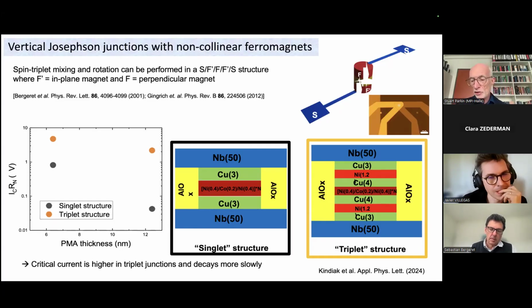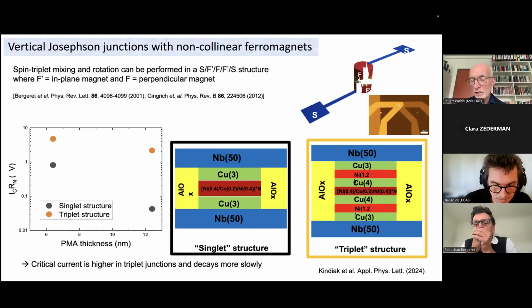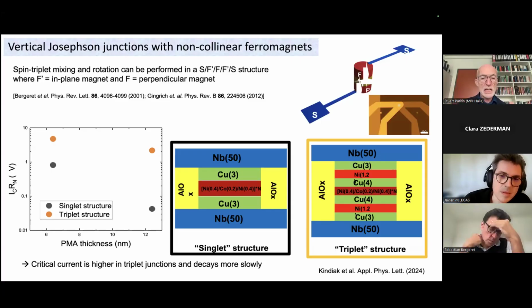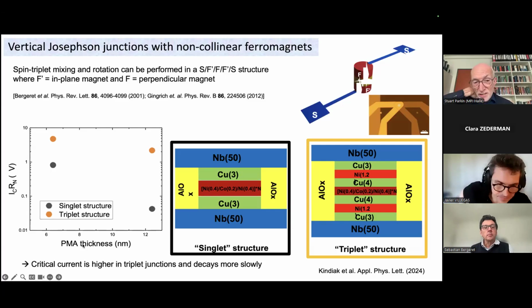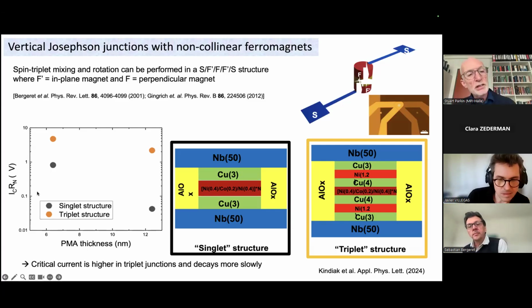So we're going to call this the triplet structure, because now, following Sebastian's prediction in 2001, we can create a triplet supercurrent that will survive over long distances, even though we've got more magnetic material on the right-hand side than in the middle. On the left-hand side, you can see the orange dots correspond to the critical currents for this triplet structure. For the same thickness of the cobalt-nickel-cobalt multilayer, the PMA thickness, the critical current density is increased almost by a factor of 10, even though we've added more magnetic material, the nickel layers.